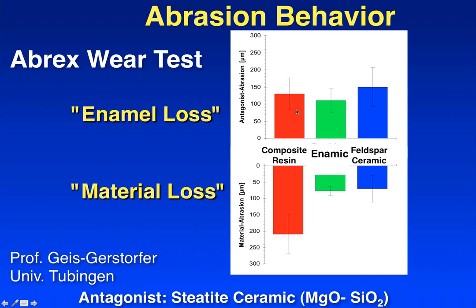So let's look at the enamel loss here. If you have a higher bar, that means that you're wearing away the enamel faster. The material that wore away the enamel the most was the feldspathic ceramic, then the composite resin, and then the Enamic. But if you do the stats, these two are the same, and the ceramic is higher than these two materials.